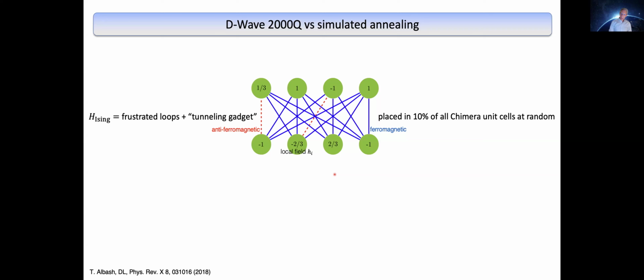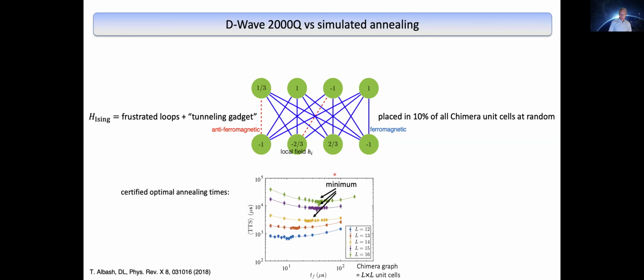So we took this gadget, we placed it in 10% of all the chimera unit cells at random, averaged over many random instances, and lo and behold, we were able to establish the existence of an optimal anneal time. So you see that very clearly here. This is the time to solution as a function of the anneal time for different problem sizes measured in terms of the size of the unit cell, the number of unit cells. And every time you see the existence of a clear minimum here, a shallow minimum, but nevertheless it's there. So the point where there is a minimum here is an optimal anneal time.